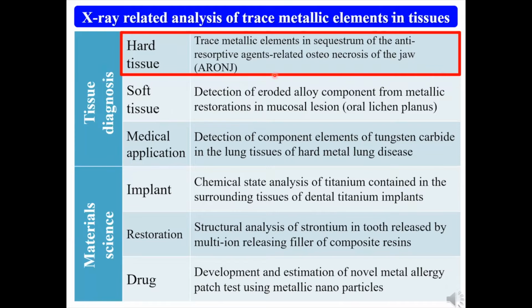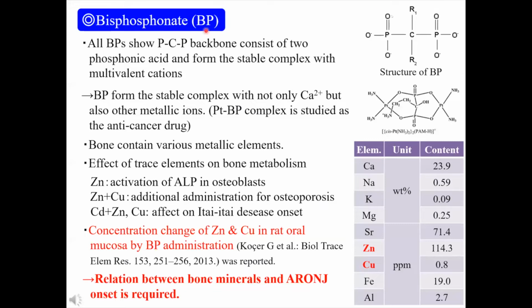The first result is the trace element distribution and accumulation in the sequestrum of anti-resorptive agent-related osteonecrosis of the jaw. Bisphosphonate, BP, is the most well-known anti-bone-resorptive agent. The anti-resorption occurs by stable complex formation between BP and calcium ion. But BP forms stable complexes not only with calcium ion, but also with other multivalent cations. For example, platinum complex is studied as an anti-cancer drug, similar to cisplatin.